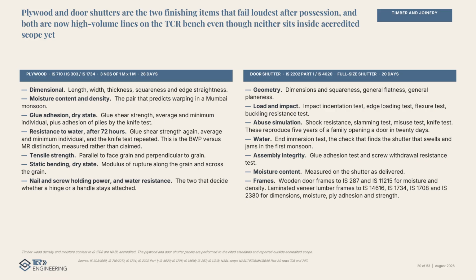Plywood and door shutters are the two finishing items that fail loudest after possession. And both are now high volume lines on the TCR bench. Plywood. 3 panels of 1 meter by 1 meter, 28 days, covering dimensions, moisture, density, glue shear strength dry, and after 72 hours in water, tensile, static bending, and nail and screw holding power. That water resistance set is the BWP versus MR distinction, measured rather than claimed. Door shutters. 1 full-size shutter, 20 days, 16 tests, including slamming, misuse, end immersion, and screw withdrawal. Both sit outside our accredited scope today, and we mark them accordingly.